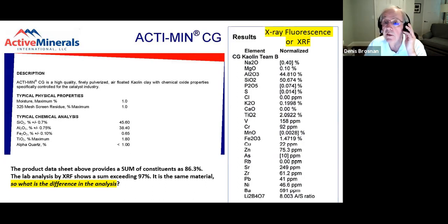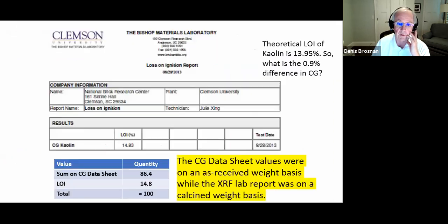So you can see that I've come up with a little bit different number than you had before. And I just want to make sure that you understand. So you can always look at a data sheet and add up the numbers. And if they add up to 100%, as in this case, then it's likely to be a calcined weight basis or ignited weight basis. Whereas if they don't, they're probably on an as received weight basis. So that's what's happened. We've measured in my laboratory the loss on ignition, and that explains the difference in the weight basis.